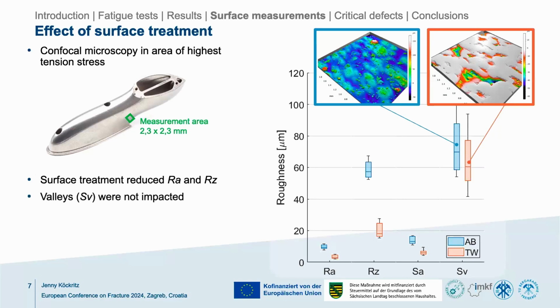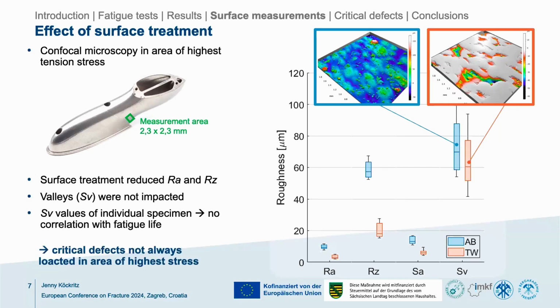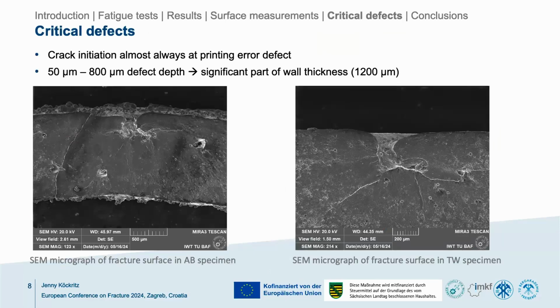So SV values were not impacted. And also, if we compare the SV values of the individual specimen with their fatigue life, we cannot observe any kind of effect, which we should see. And the reason for that is that the critical defects actually are not always located in the area of high stress in these parts. So let's have a look at these critical defects.